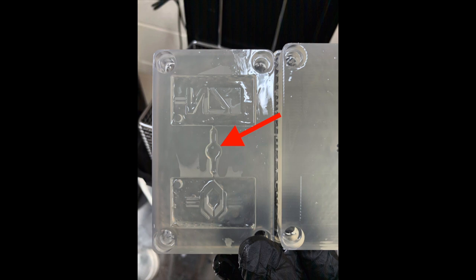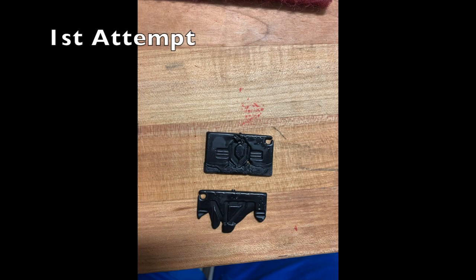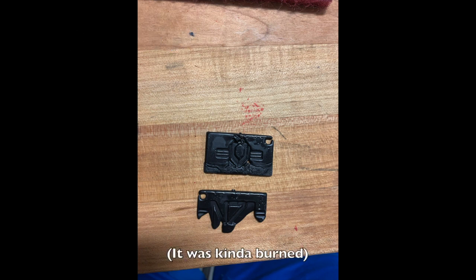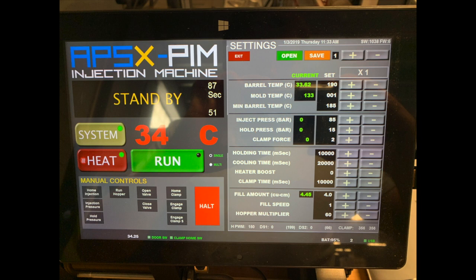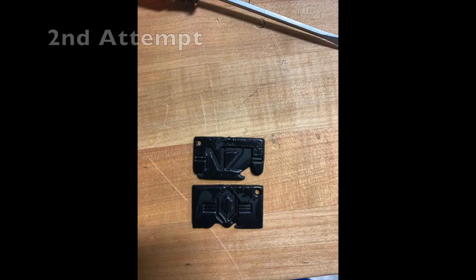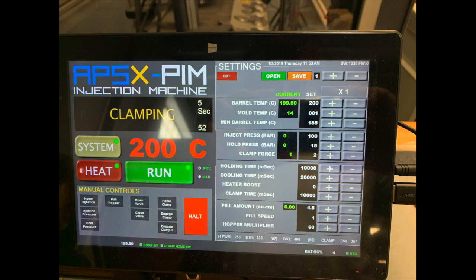For our second attempt, we increased the fill amount because the mold didn't get completely filled last time. Because we noticed some burn spots on our first attempt, we raised the barrel temp on the machine. To try and avoid the sprue getting stuck again, we increased the injection pressure as well. Once again, we increased the fill amount because the mold was still not being completely filled.